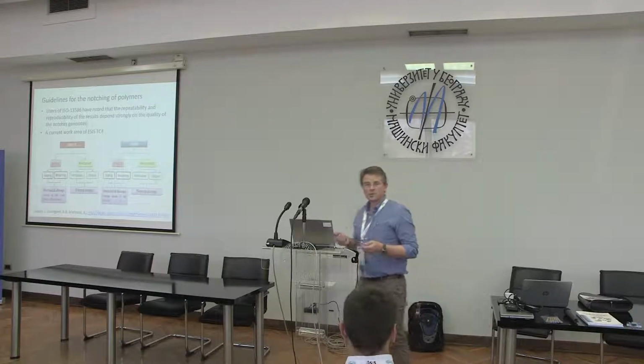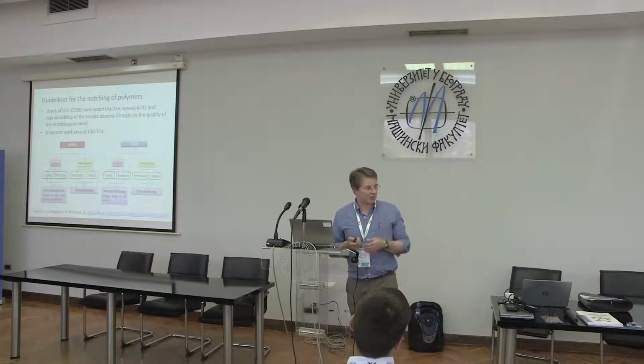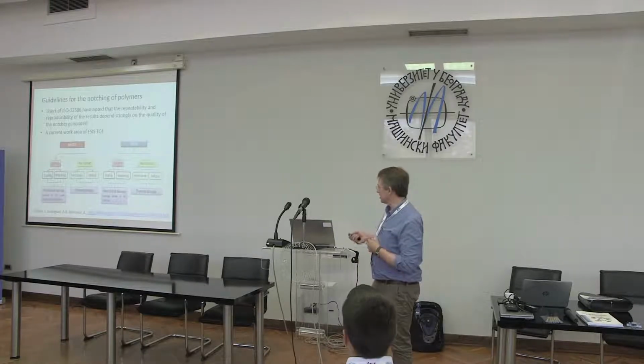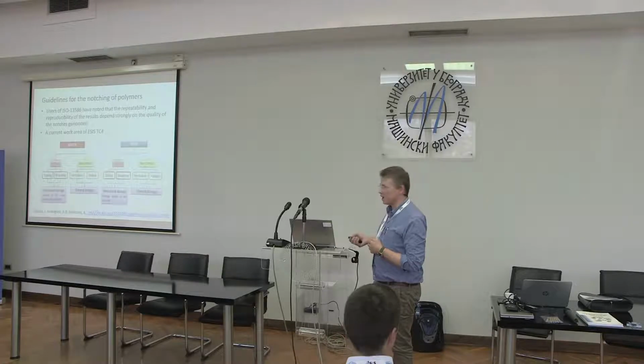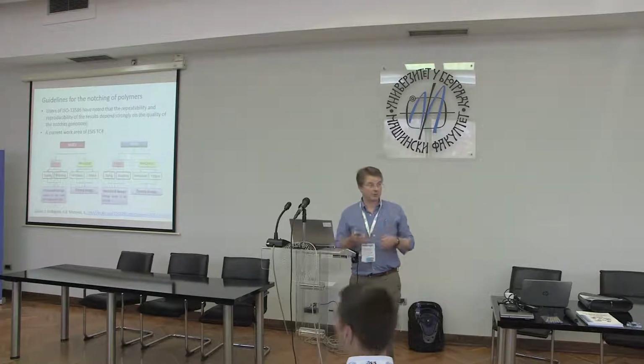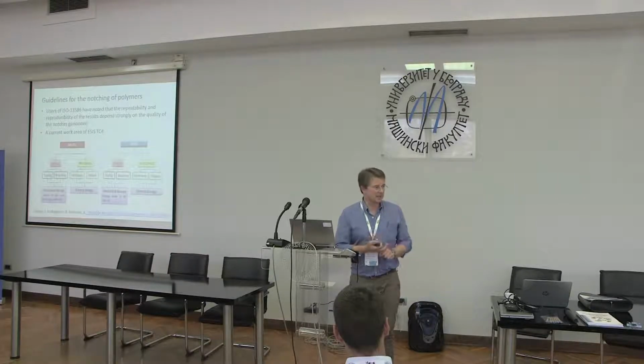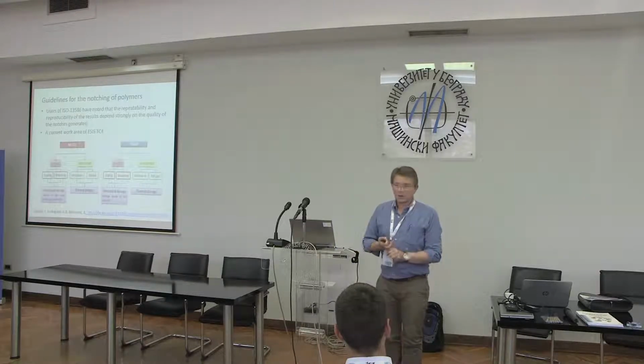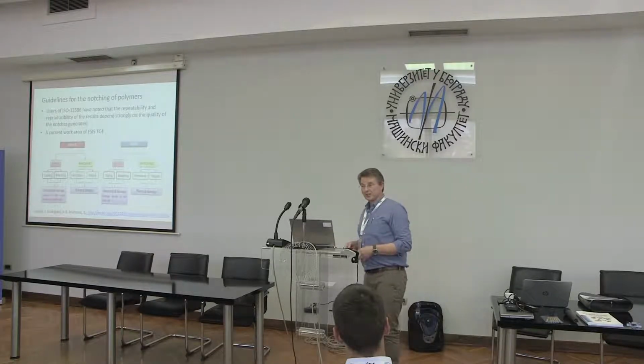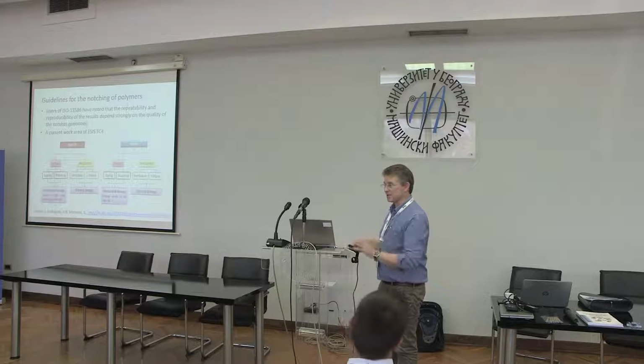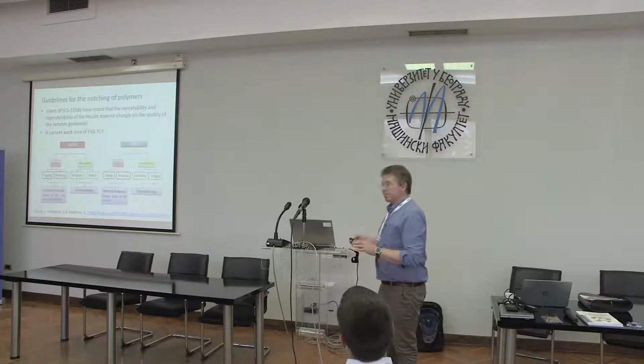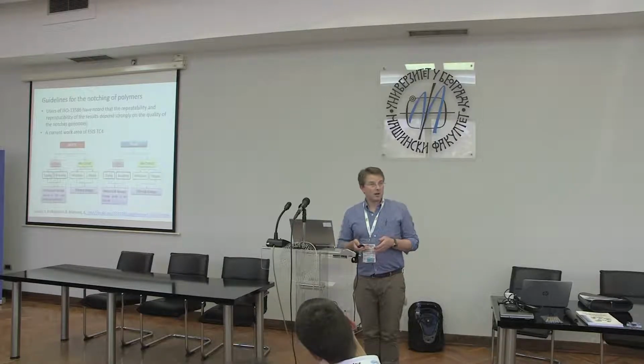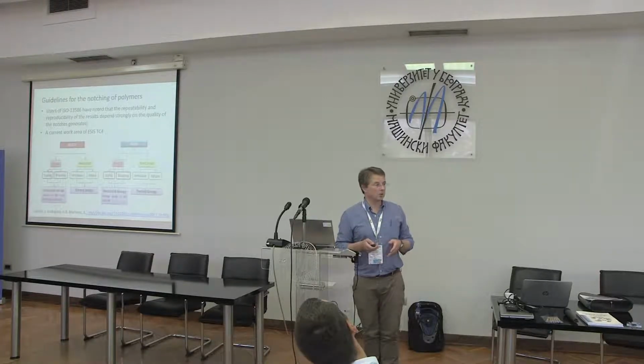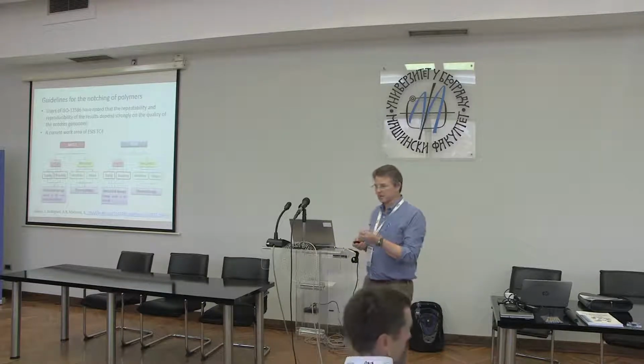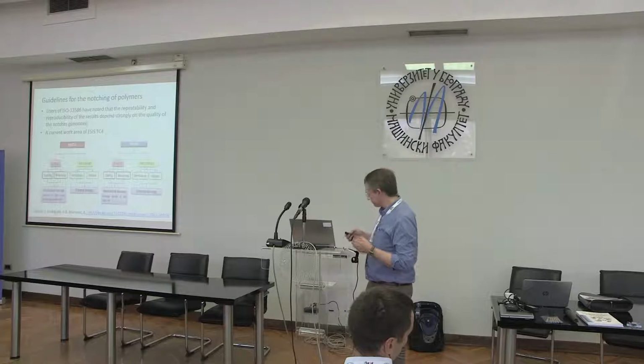There was some interesting work on using femto lasers to generate these cracks. This was some work that was done at Catalonia in Spain, and the femto laser notching was used, and initially this looked really exciting. Apart from being an incredibly expensive method, I think it cost €50 per sample, which choked most of us, but it looked initially very encouraging that we could all invest in femto lasers to make these notches. Unfortunately, it then became apparent that although they were quite sharp, there was a problem with them, and there had been thermal damage to these crack tips. So even these incredibly fast lasers were damaging the polymer. So we needed another approach to this.